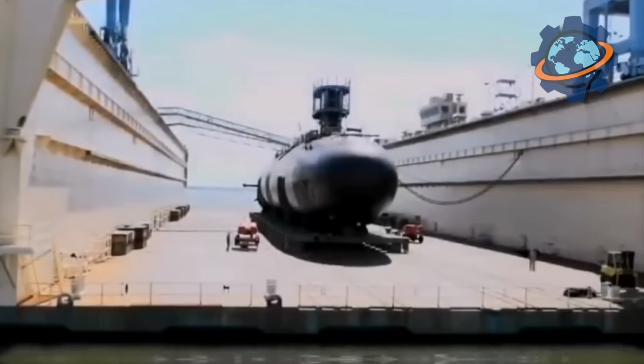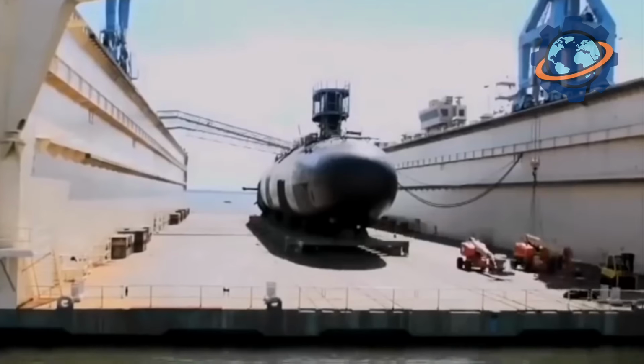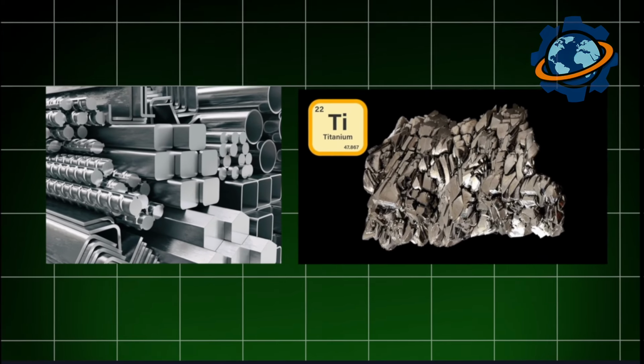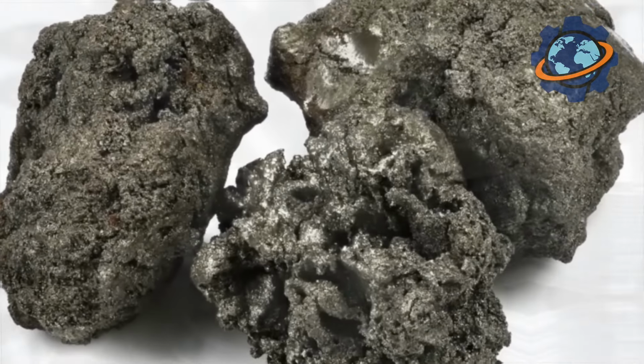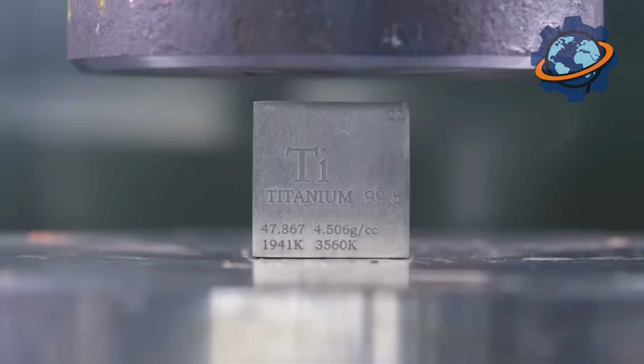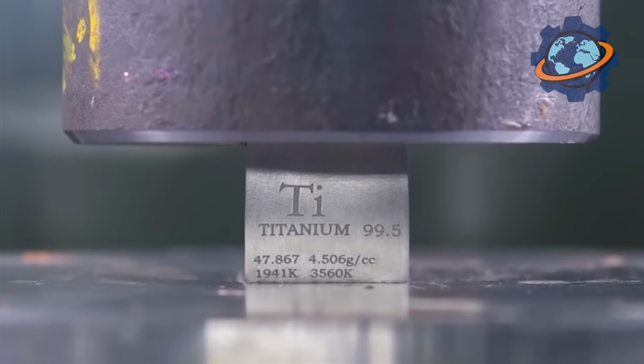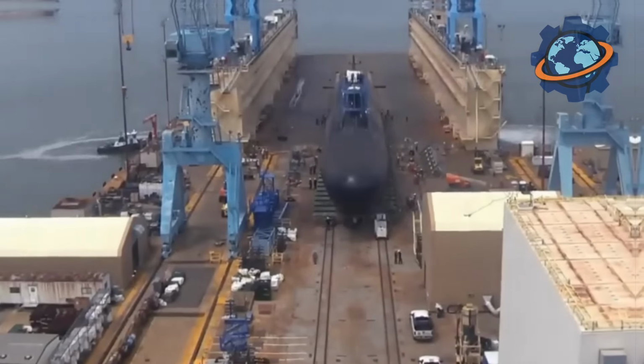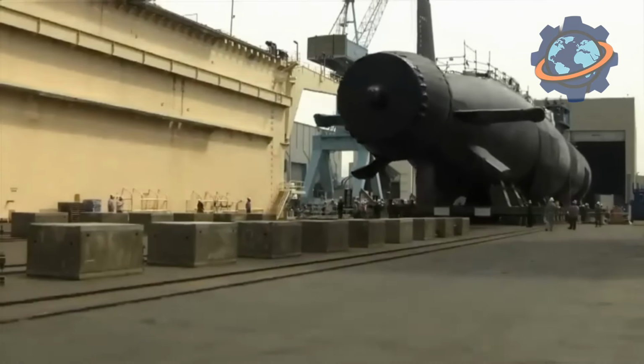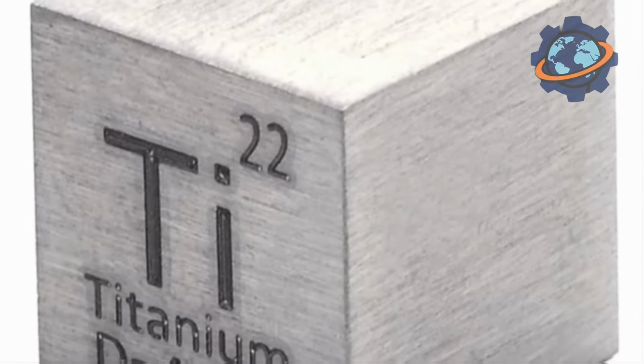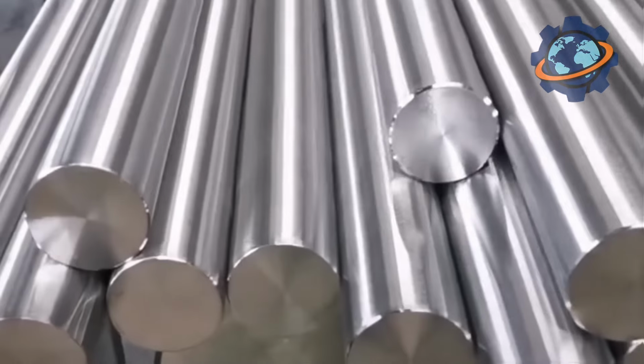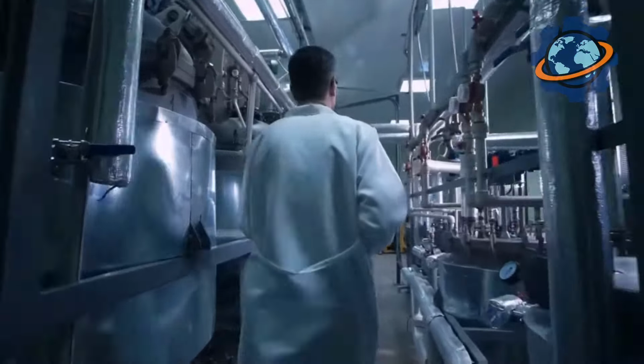For the construction of nuclear submarines, special materials are used that can withstand high pressure at great depths and provide protection against corrosion. Usually, these are high-quality steel or titanium alloys. Steel is cheaper and easier to produce, and it withstands pressure and impacts well. Titanium has the advantage of high strength, lightness, corrosion resistance, and being non-magnetic, which makes it harder to detect the submarine. However, titanium is more difficult to process and weld, as its melting point is higher, about 3,092 degrees Fahrenheit, versus approximately 2,552 degrees Fahrenheit for steel.